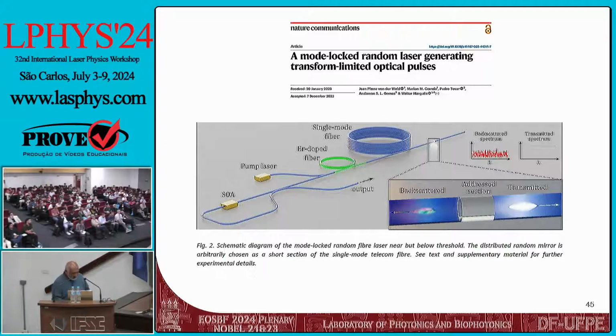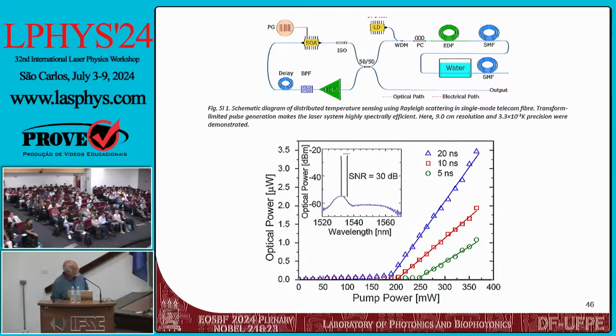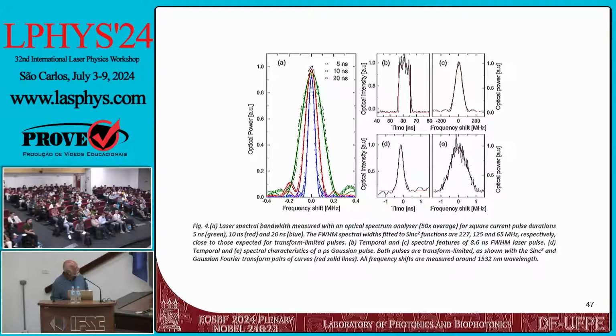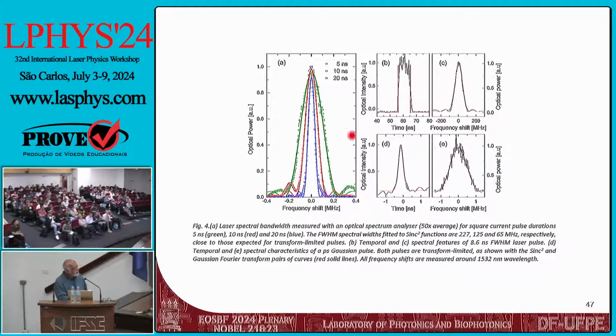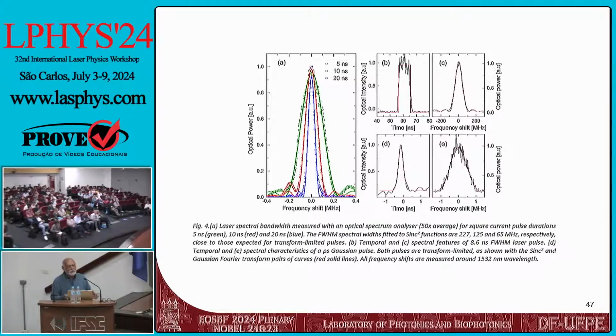That was, again, based on what we had here for our loop mirror. We had the single-mode fiber and the erbium fiber to act as an amplifier. And exploiting the Rayleigh scattering in a few centimeters of fiber, we could see the short pulse. We generated about 300 picoseconds. Let me jump to the result here. We generated about 300 picoseconds, and this was transform limited. So that was the first time it was generated. It can then be amplified. It's in a fiber, so it's directional, and then we can exploit that for different applications.